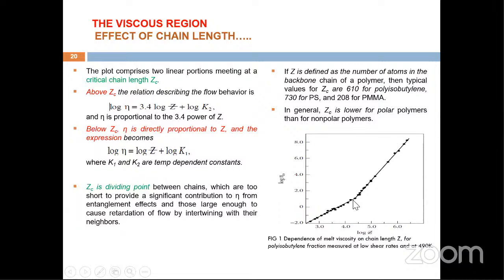The chains below this point are too short, so they have no significant contribution to the viscosity from entanglement effects, we must know that. And above this point, chains are long enough that they retard the flow. So the main effect takes place around here. Z is defined as the number of atoms in the backbone of the polymer chain. For example, in the case of polyisobutylene, this critical chain length value is 610. So around 610, viscosity is more affected by other conditions.